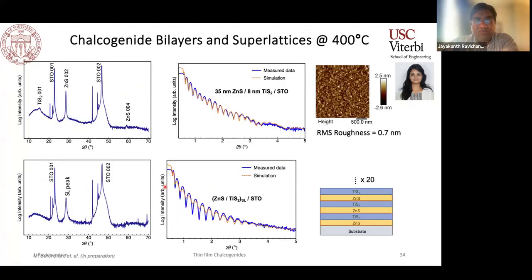Okay, so with that, I want to show a brief, quick demonstration of our ability to grow chalcogenide bilayers and superlattices. Since there are still challenges in the ternary system, we resorted to growing these structures using the binary systems such as zinc sulfide and titanium sulfide. You can see that you can get fairly smooth bilayer structures. The superlattice reflections do show up.